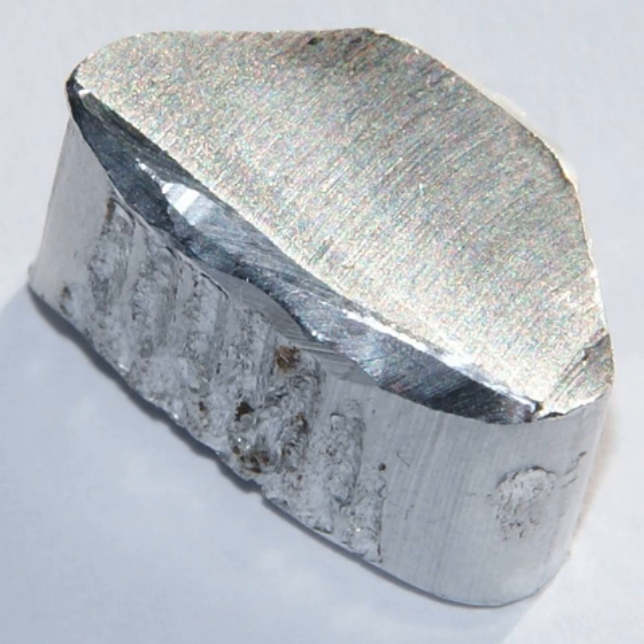An aluminium stack melter produces significantly less dross, with values reported below 1%. White dross from primary aluminium production and from secondary recycling operations still contains useful quantities of aluminium that can be extracted industrially. The process produces aluminium billets, together with a highly complex waste material. This waste is difficult to manage. It reacts with water, releasing a mixture of gases including, among others, hydrogen, acetylene, and ammonia, which spontaneously ignites on contact with air. Contact with damp air results in the release of copious quantities of ammonia gas. Despite these difficulties, the waste is used as a filler in asphalt and concrete.